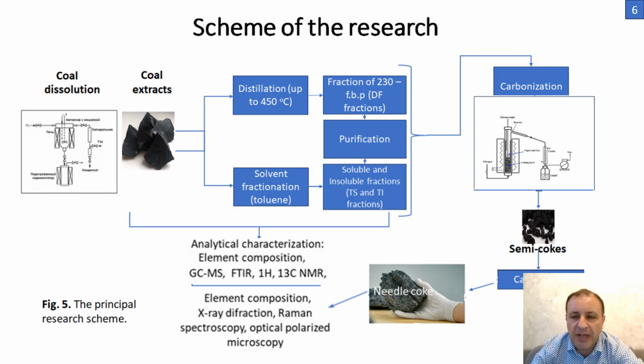The resulting coke was obtained in two stages. The first stage was carried out at a temperature of 475 degrees Celsius for 5 hours of soaking time. The reaction pressure was maintained at approximately 0.8 megapascal, and excess pressure was released through a control valve. The first stage carbonization products, named semi-coke, were subjected to higher temperature coking in a ceramic crucible with ground lead in a muffle furnace under an inert atmosphere at 1100 degrees Celsius for 1 hour. All obtained products, such as various fractions, semi-cokes, and calcined cokes, were investigated by multiple methods, including GC-MS, Fourier transform infrared spectroscopy, and nuclear magnetic resonance spectroscopy.